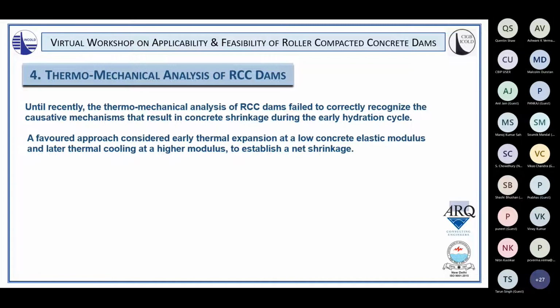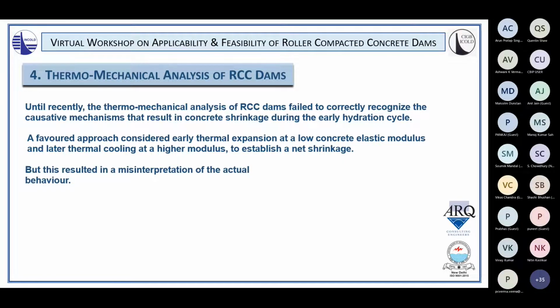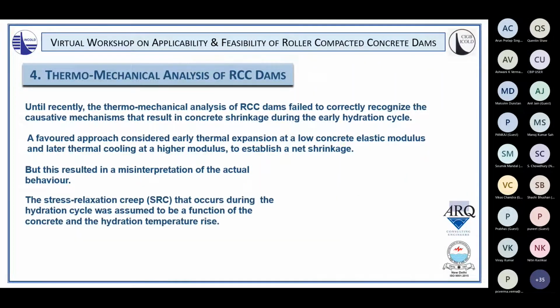Thermal expansion at a low concrete elastic modulus, and later thermal cooling at a higher concrete modulus, with basically the difference creating a shrinkage of that concrete. But this approach actually resulted in a misinterpretation of the actual behavior of the concrete. And stress relaxation creep that occurs during the hydration cycle was assumed to be a function of the nature of the concrete and the hydration temperature rise. And this was applicable essentially for all approaches used for the thermomechanical analysis of all concrete dams, essentially.